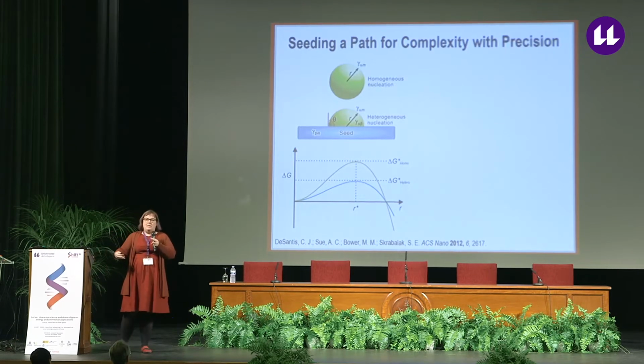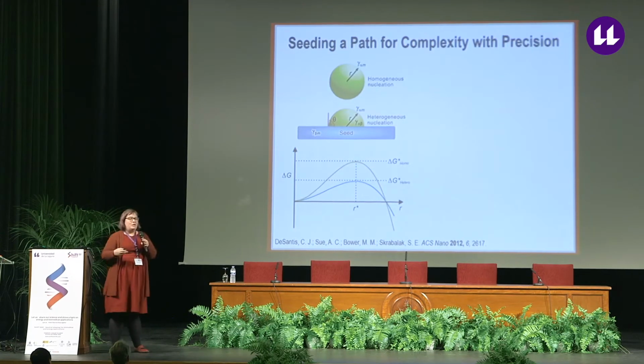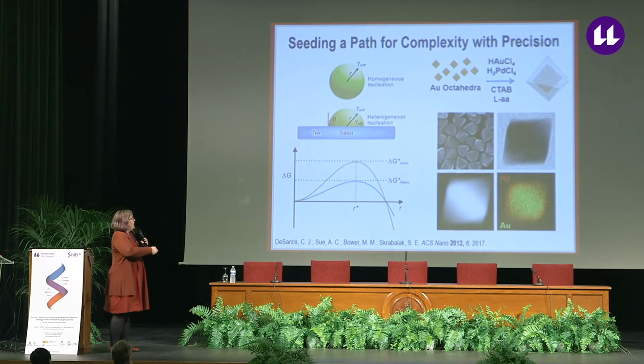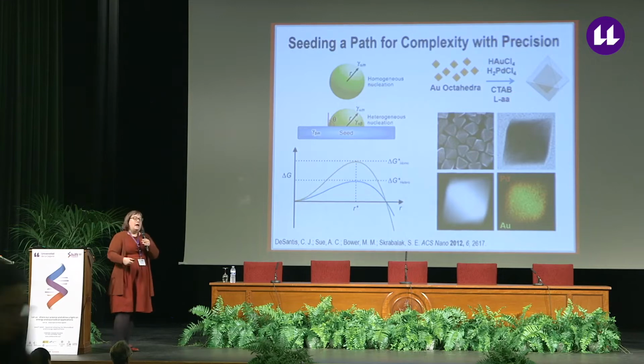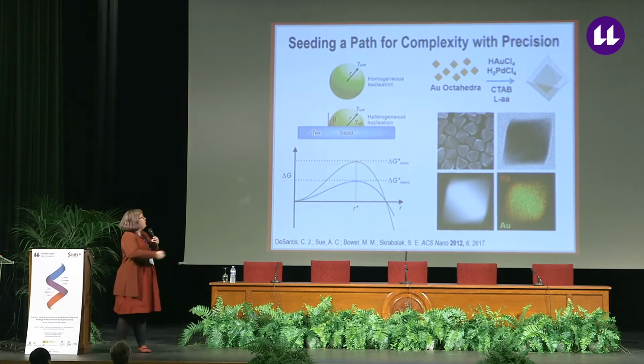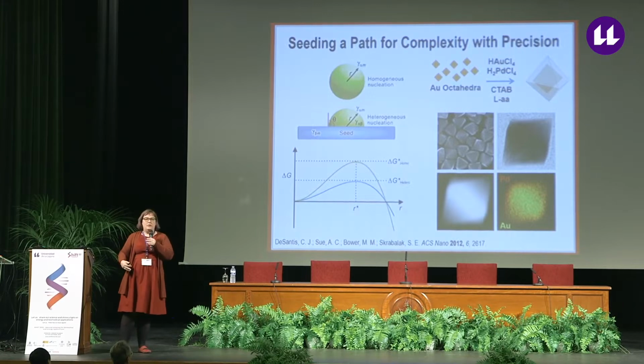And so as an initial demonstration in my group, we were interested in just getting shape-controlled alloyed nanoparticles. To do this, we decided to start with gold octahedral seeds. They're dispersed in an aqueous solution with CTAB as a capping agent. And then we are going to co-reduce gold and palladium salts using ascorbic acid as a reducing agent.